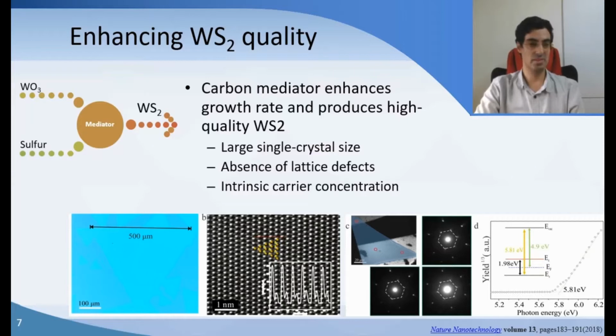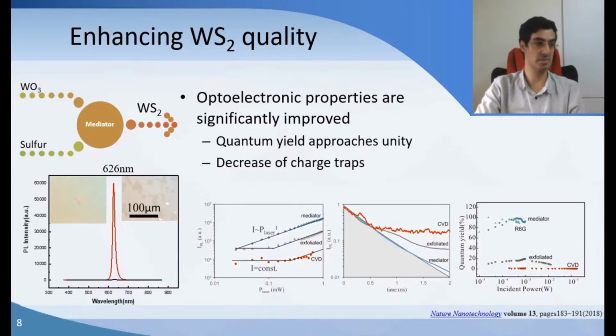That can also be shown by spectroscopy. Photoelectron spectroscopy shows that the WS2 has pretty much an intrinsic Fermi level, where you would expect it, at half of the band gap. We can also check optics, and we find that the photoluminescence intensity of WS2 is orders of magnitude higher than for normal CVD growth. And if we check power dependence, we observe that even at low powers it has a linear dependence of emission intensity on excitation intensity. And that's a sign that there are fewer traps.